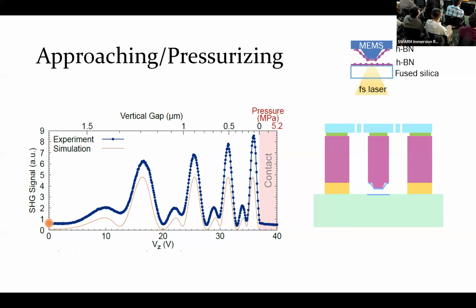And now I want to show you what we have done so far and what we can potentially do with these new devices we developed. In this study we are using hexagonal boron nitride, which you recall is an excellent electrical insulator, but it's also an interesting optical material because it has interesting nonlinear properties. Which means that if we shine a red light into the system, a femtosecond laser, and focus on the hBN, it will generate blue light by a process called second harmonic generation.